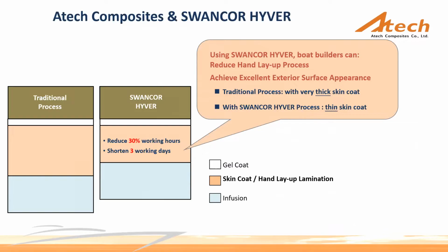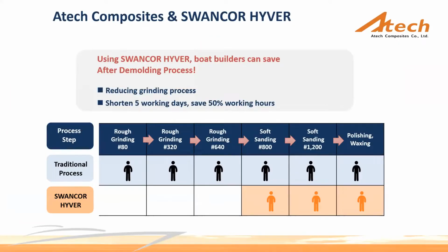For luxury yachts, hand lamination is necessary, but it is really time-consuming. By using HYVER resin, we can save labor hours and construction days in the hand lamination stage, and we also keep the same surface quality. Also, in some cases, the builder builds the boat by the infusion process, but the skin coat is thin. So after demolding, we usually see a really bad surface.